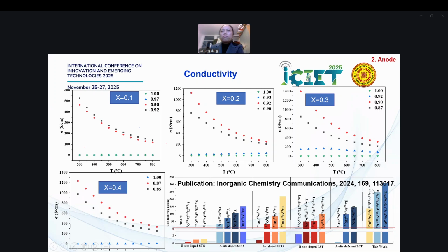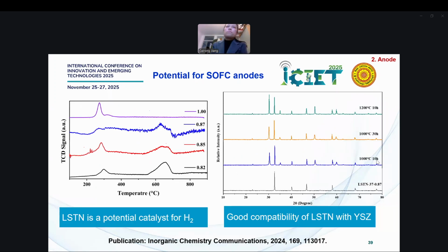Compared with the reported values, our work on the right-hand side is quite high. It's a few hundred at 800. We compare at 800 because this is a common temperature we use for the cell's operation. And for potential use as fuel cell materials, we tested the catalytic activity towards hydrogen. So it seems it's a good catalyst for hydrogen.